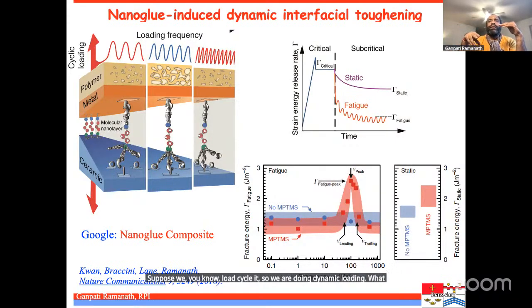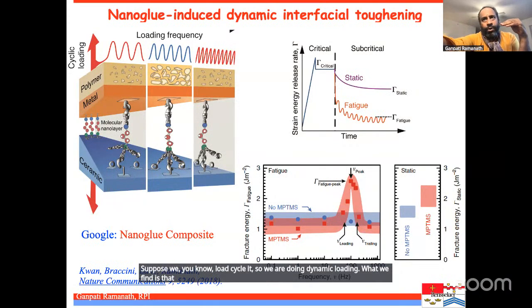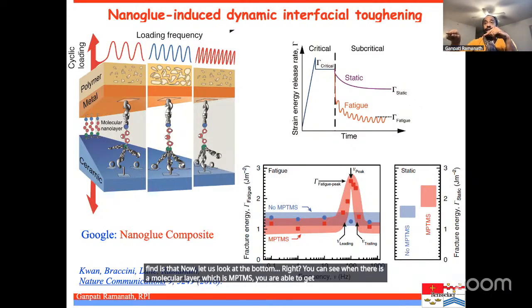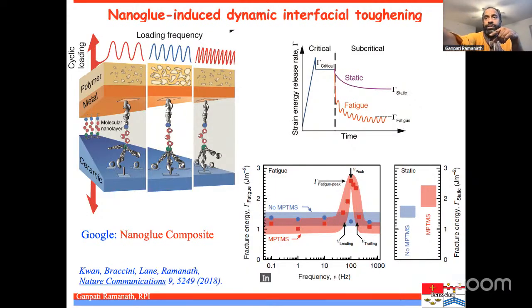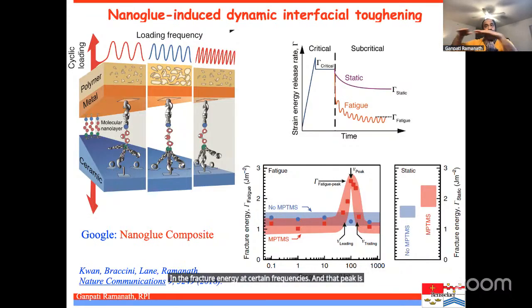What we find is that, now let us look at the bottom right. You can see when there is a molecular layer, which is MPTMS, you are able to get a peak in the fracture energy at certain frequencies. And that peak is absent in the blue curve, which has no molecular layer. And this is very significant because,